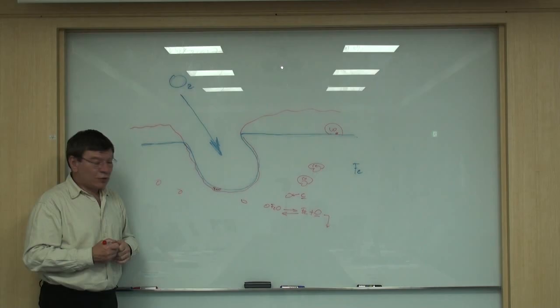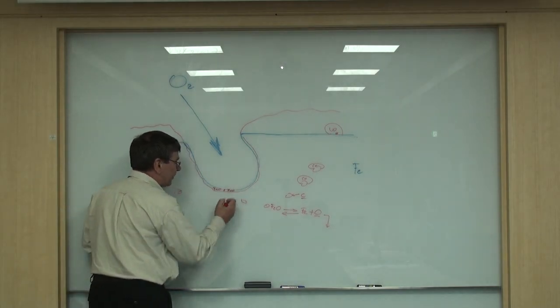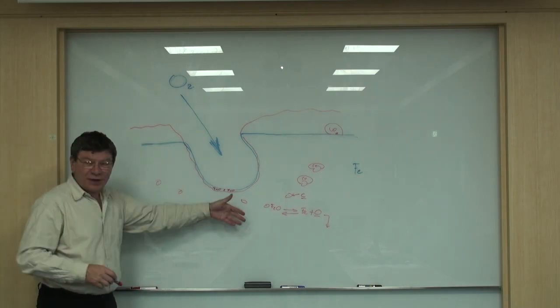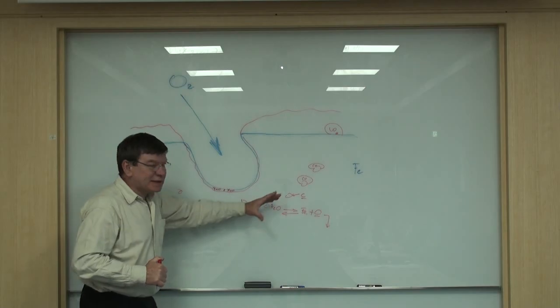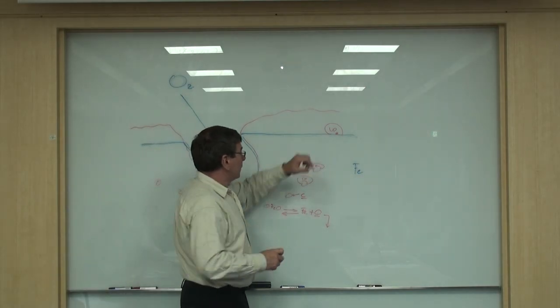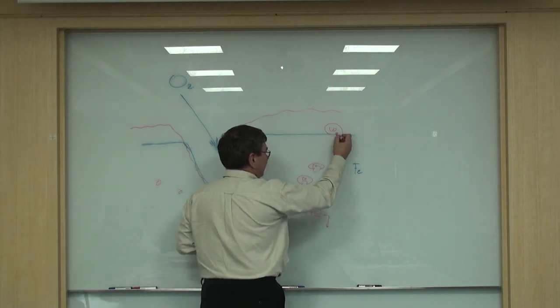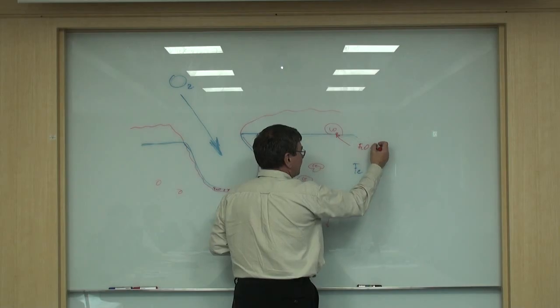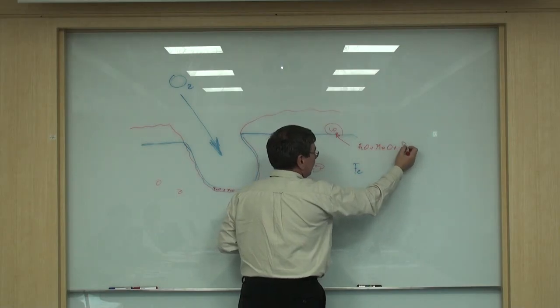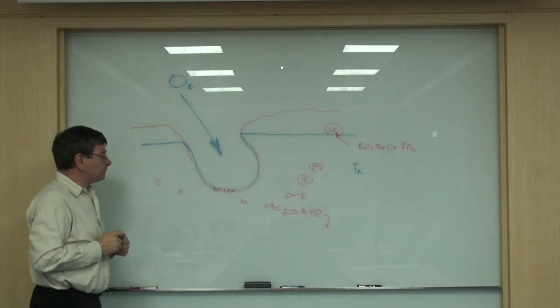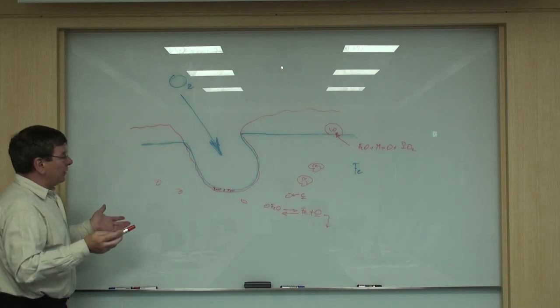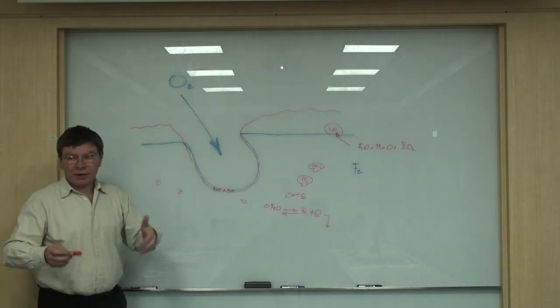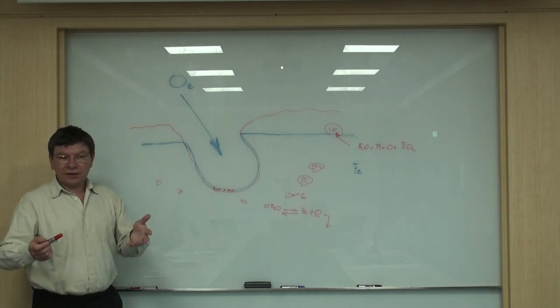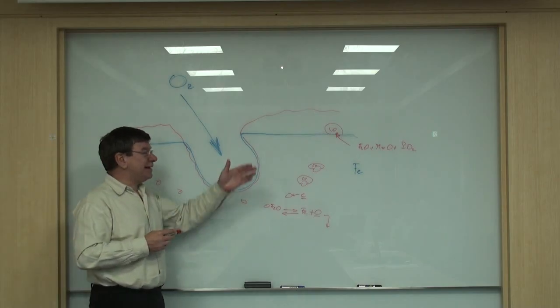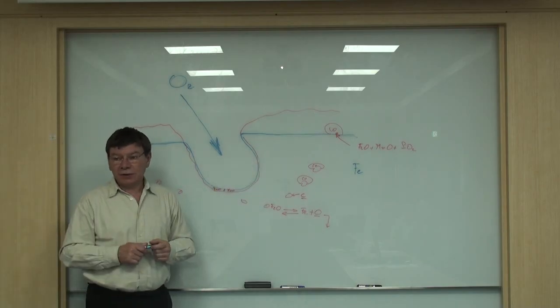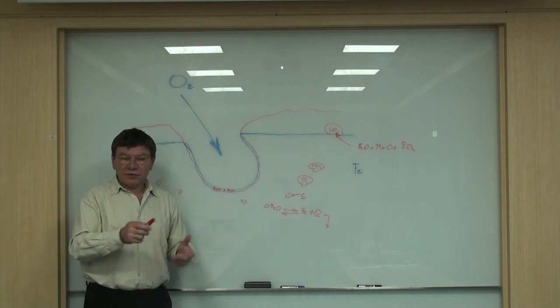If you have high manganese, of course, you create FeO plus MnO. Yeah? If you have high silicon, you create as well silica. Alright? So you have a primary slag here coming to the top. At the end here, you have a mixture of FeO plus MnO plus SiO2. Okay? So if you don't do anything, your slag is getting richer and richer in FeO. I've seen steel plants having at the end up to 50% FeO in the slag. And they don't care so much. They don't take slag analysis.